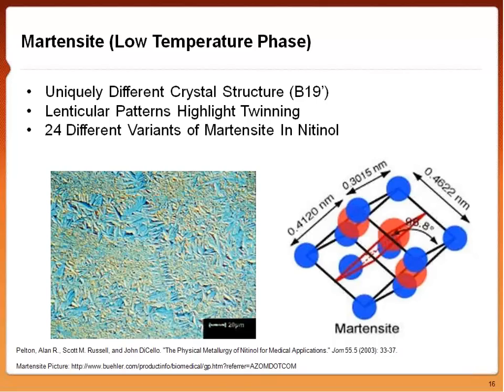Another reason why we're able to accommodate this low temperature phase is that there are 24 different variants of martensite in nitinol. When we look at the crystal structure over here, we can see it's a little bit more complex and a little bit less symmetrical than that B2 structure we saw with austenite.